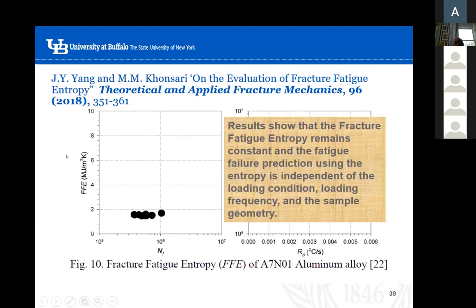You are applying the same load again. For example, the average mean stress level for this sample is, of course, smaller than for this one. So that's why this one is failing earlier, because the stress is higher. And this one has a smaller stress. As a result, it fails at 1 million cycles. So if you plot an S-N curve, if there are 6 or 7 samples, you will have 7 different S-N curves. However, what is unique is the total entropy value at failure. They all fail when the thermodynamic state index is 1.